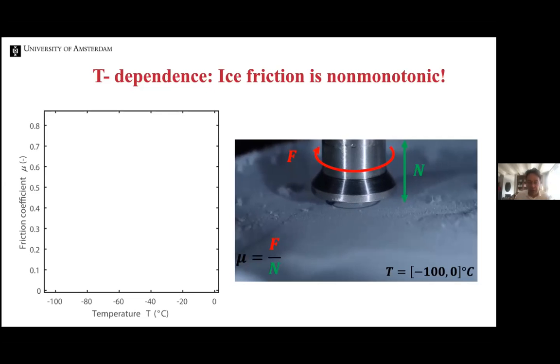and we'll see where we get with the friction on ice. So we plot this friction coefficient as a function of temperature, and then we get our first surprise, namely that the ice friction is completely non-monotonic and does all kinds of interesting things. So if I'm at -100 degrees C, we're actually a little bit below even, we get a friction coefficient of roughly 1/2. And that is a friction coefficient that is typical of your foot sole on the pavement, meaning that you cannot slide at all.